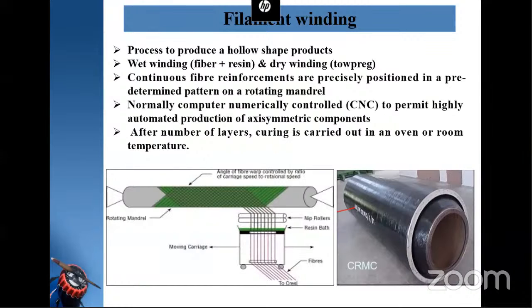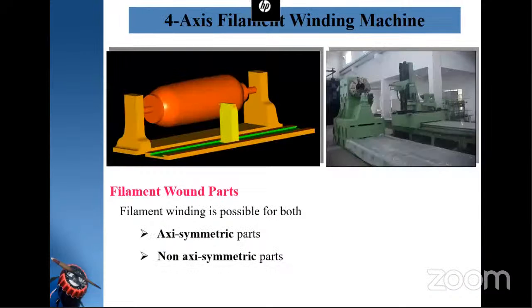This is a computer numerically controlled machine which has 4 axes or 5 axes. We can place the fiber at whichever angle we desire or the designer prefers. We can place it across, or at an angle to the axis of the component, or parallel to the axis of the component, so that we will get an optimum structure to carry the desired loads. After a number of layers, curing is carried out in an oven, and finally the component can be extracted by removing the mandrel, and the cylindrical component can be extracted.